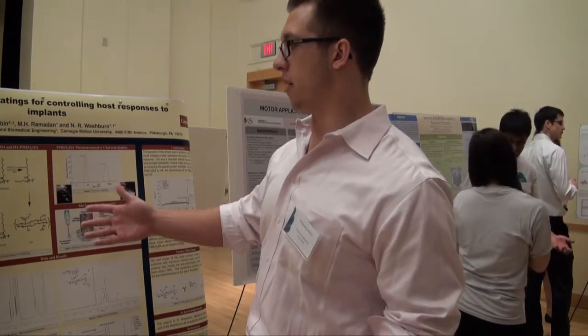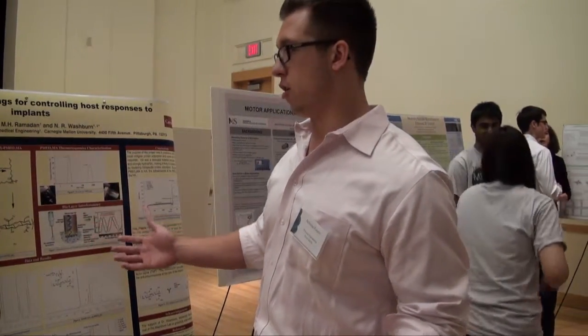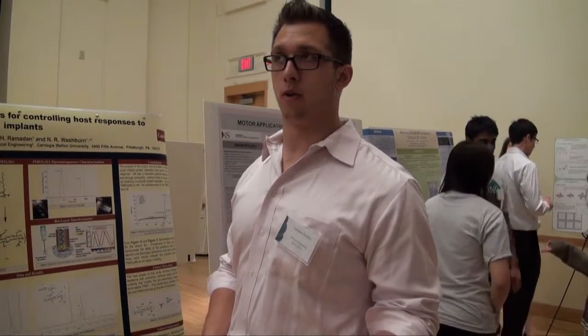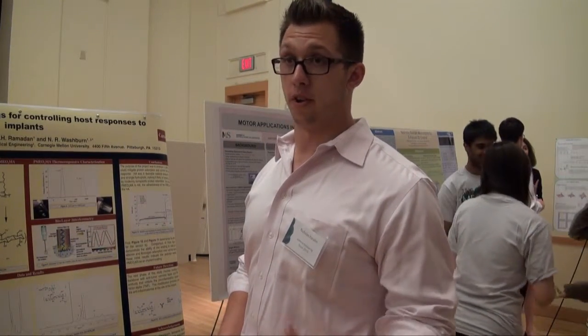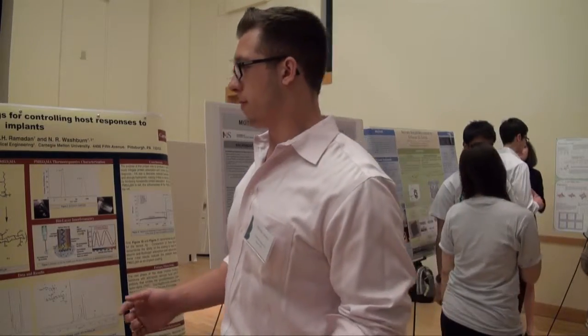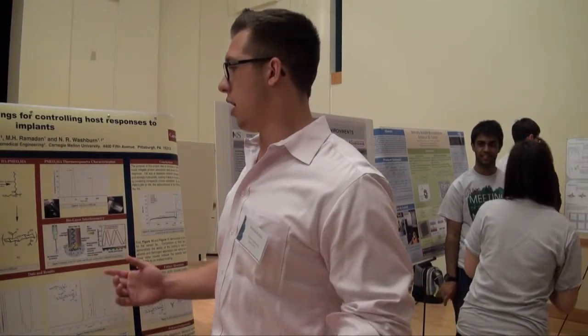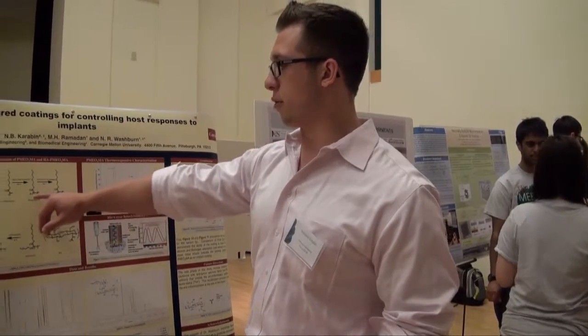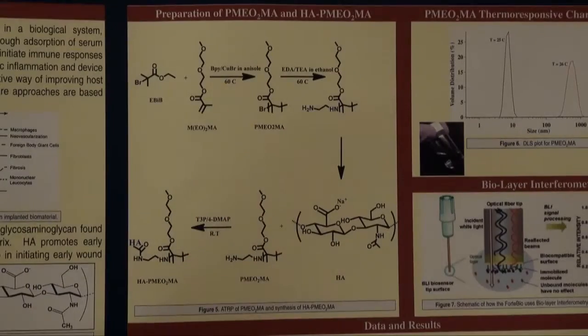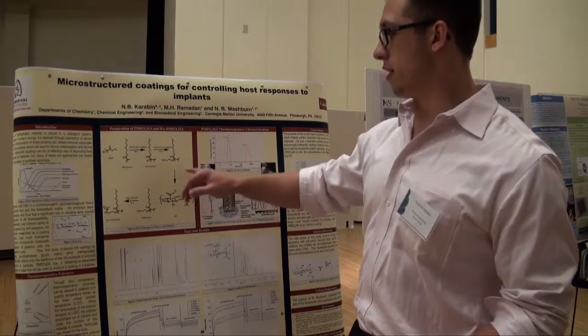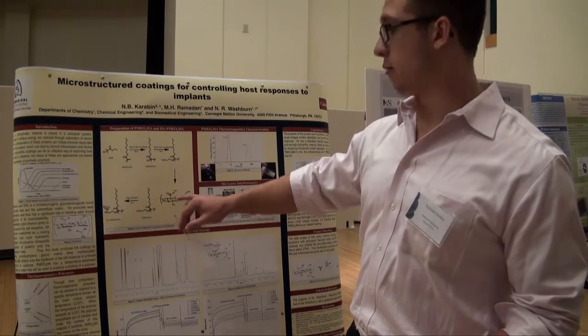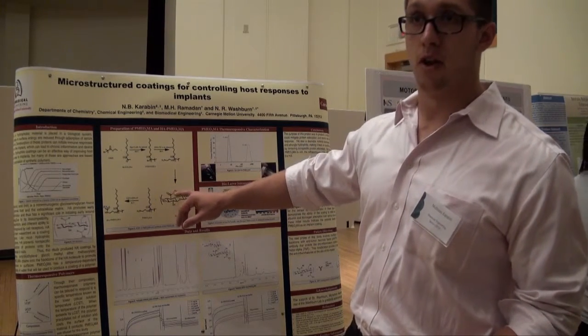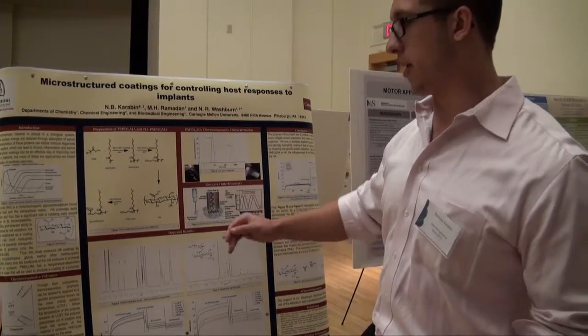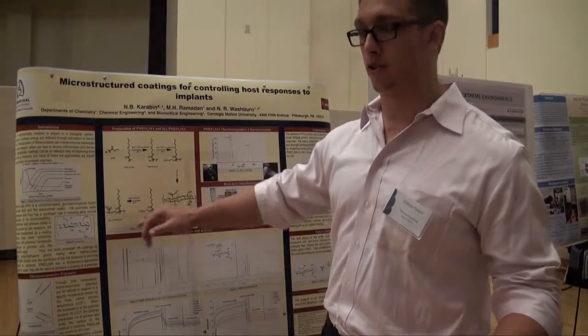This area is simply the synthesis behind the polymer. We use ATRP, which is atom transfer radical polymerization. It's a controlled method in which we first synthesize the polymer, then we substitute this bromine group with ethylene diamine, allowing us to have a free amine group. With this free amine group, we can then bind the polymer to the HA by reacting the amine group with the carboxylic acid group that's in every repeat unit in the HA. And that allows us to develop this HA polymer construct.